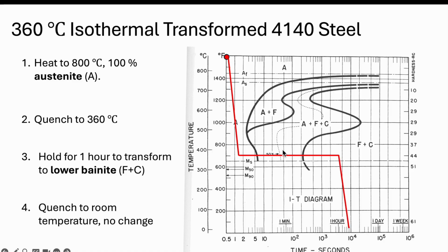And so I want to add one last thing that I put on these diagrams that isn't necessary, but I always like to show that it's at 360 degrees. held for roughly an hour. That's how we do it in the lab. And then after that, we have to cool it to room temperature. We're not going to hold it at 360 forever. So after that hour, we rapidly cool to room temperature.